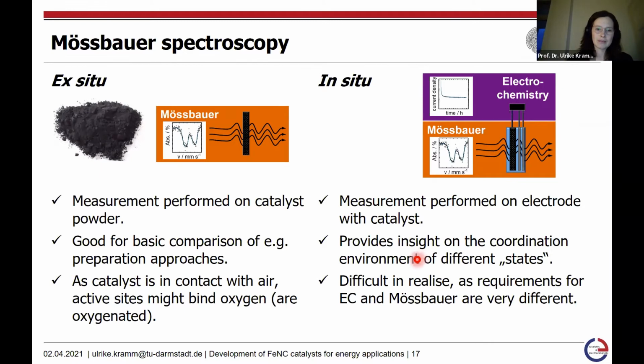What needs to be mentioned is that it is quite difficult to realize this, at least for our catalyst material. I mentioned we have a lot of iron inside, but a lot of iron means in this case something like 3 weight %. And as Mössbauer spectroscopy is limited to one specific isotope of iron, we basically always need to work with fully enriched samples in order to enable this kind of experiment, which is quite expensive, but of course it gives us a lot of reasonable, nice insights.